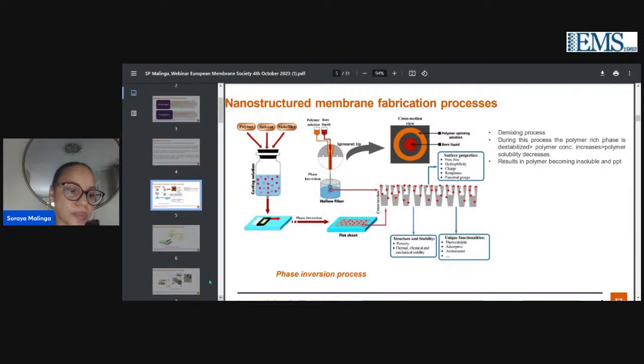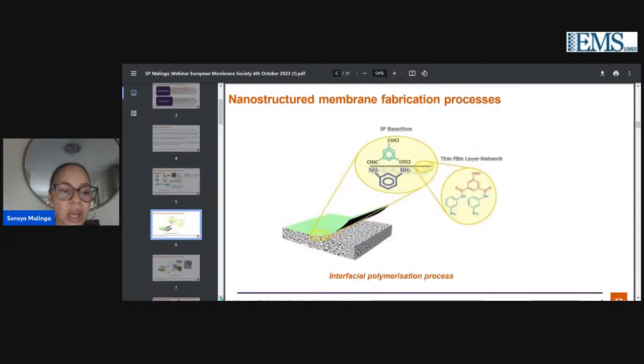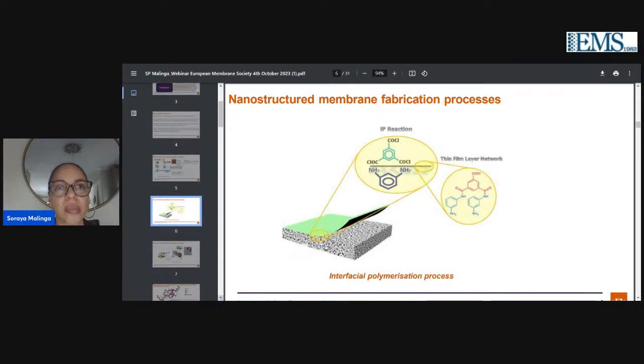We've also used interfacial polymerization, where we have formed a very thin film active layer on the membrane using a commercial membrane as our support. Since my research is more geared towards the use of hyperbranched polymers, for the amine terminated, where you would use MPD, we would use a hyperbranched polymer, which also has NH2 functionalities. And with its reaction with your trimesoyl chloride at the interface, it will form a very thin film.